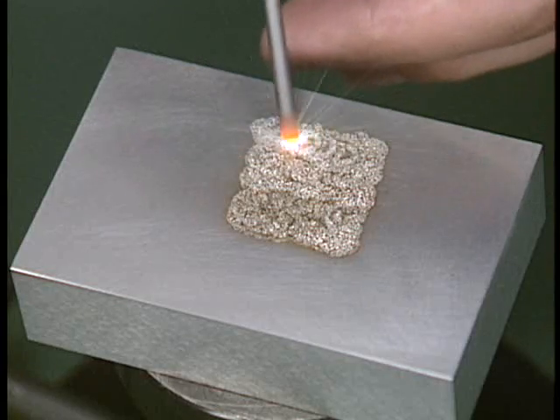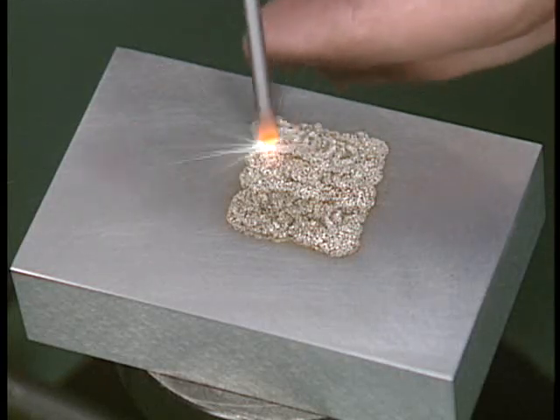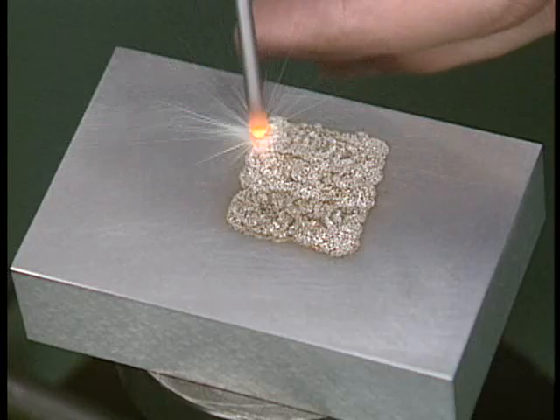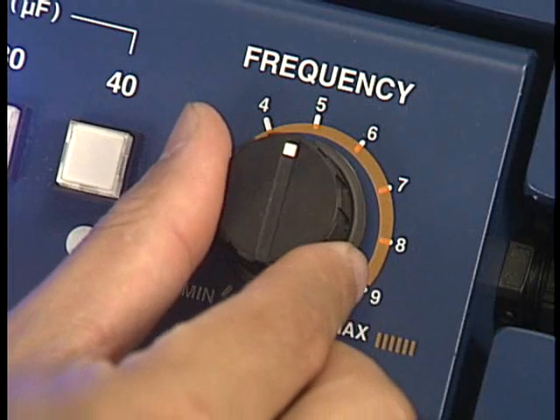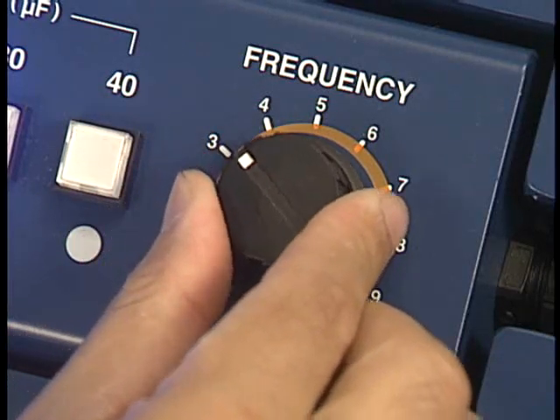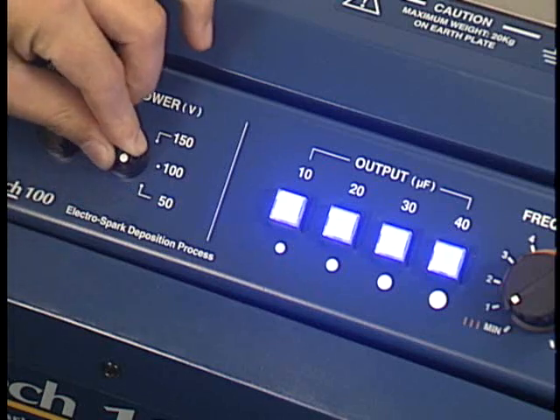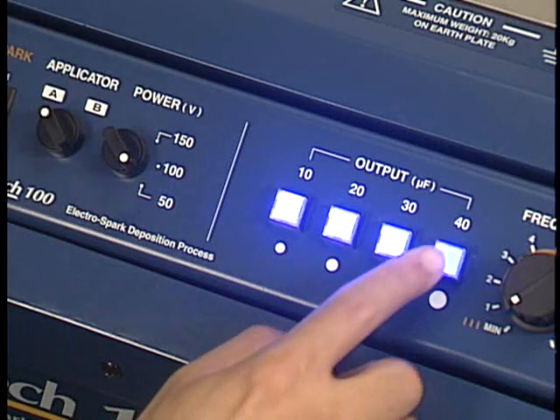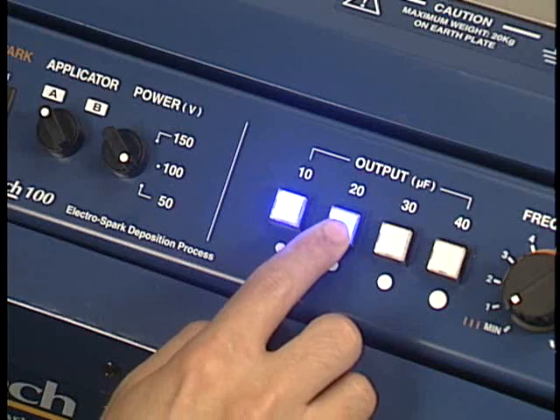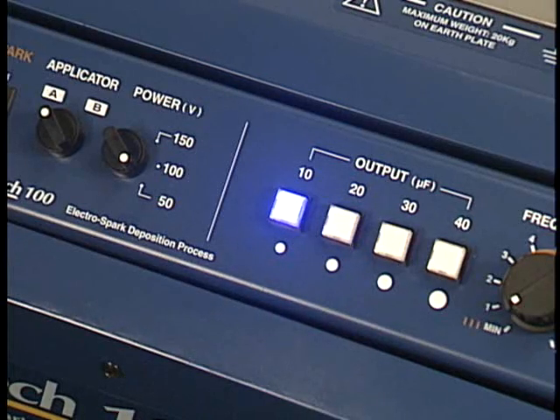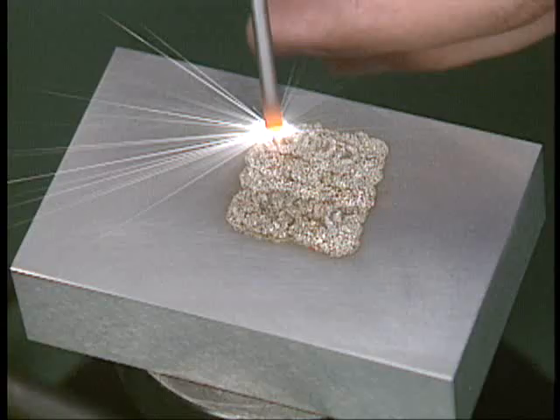Reduce the frequency, the output or power levels when the tip of the electrode becomes red. If coating is applied while the electrode tip is red, different compounds may be introduced into the coating than those of the electrode material. Make sure the tip of the electrode is not red to obtain optimum quality of the coating.